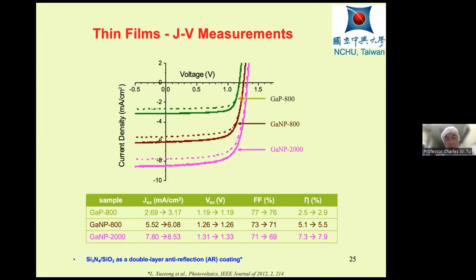IV curves. So you can see this dilute nitride has a higher efficiency. Okay, higher efficiency. So this is a larger short circuit current. Small change in the open circuit voltage, and then this is the fill factor. And then here is the efficiency, and the larger number here is with anti-reflection coating.